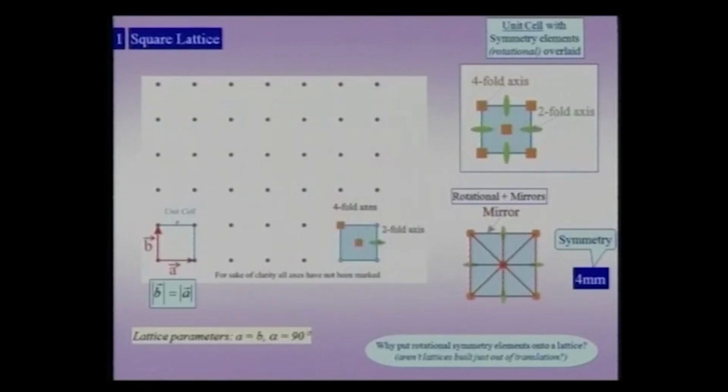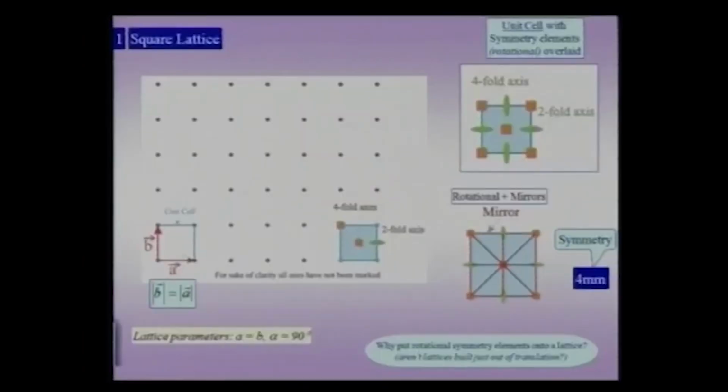Similarly, if you have a green colored 2-fold axis sitting here, and if you have the A lattice translation vector, in this case I would consider a minus A, then automatically there has to be a green 2-fold axis which has to sit here, and correspondingly here, correspondingly here, correspondingly here. In other words, if I can locate one symmetry operator anywhere in the lattice, then this symmetry operator would also go ahead and completely fill up this 2-dimensional lattice or space given these 2 lattice translation vectors.